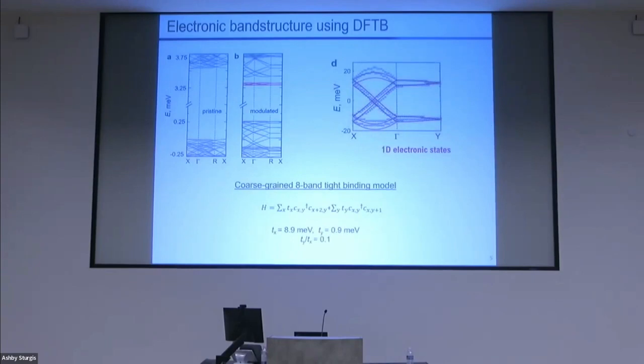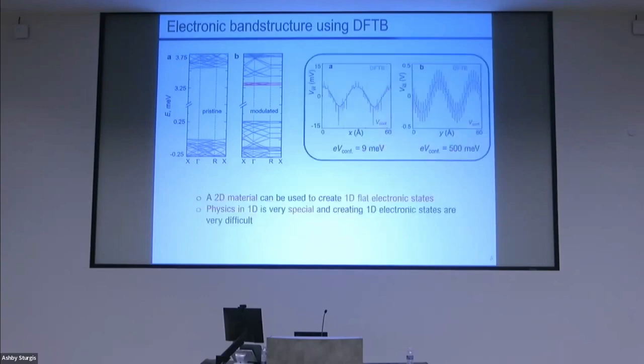In order to confirm that these are 1D states, I use the coarse-grained eight-band type model to fit this band structure. Here is the same band, and the red bands as fitted are fitted using the simple tight-binding type model. From this tight-binding type model, I get that the Hamiltonian has anisotropic hopping along y with a specific value at the saddle point. This confirms that these are 1D electronic states.